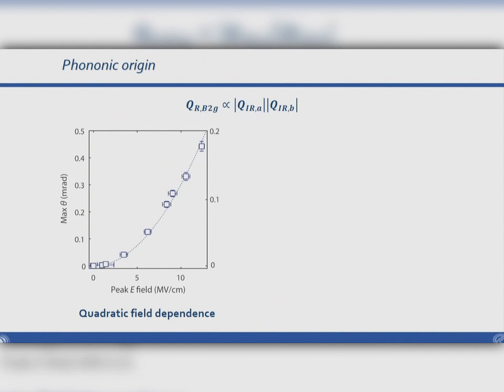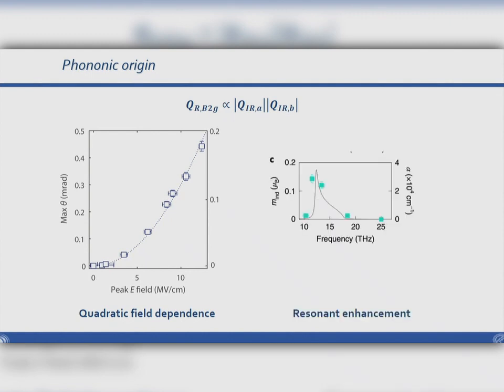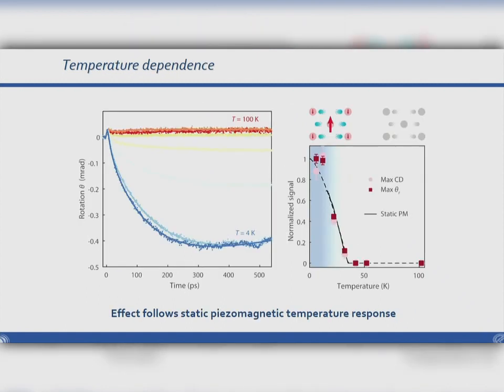So we can study this effect as a function of the electric field that we apply to our sample, and indeed you observe a quadratic field dependence, which totally makes sense because each of the modes you drive linearly with the electric field. And if you now tune your excitation frequency over a broader terahertz frequency range, you see that the amplitude of our signal is resonantly enhanced if you're indeed in resonance with these degenerate optical phonons that we believe to resonantly excite. Okay, so everything here makes sense.